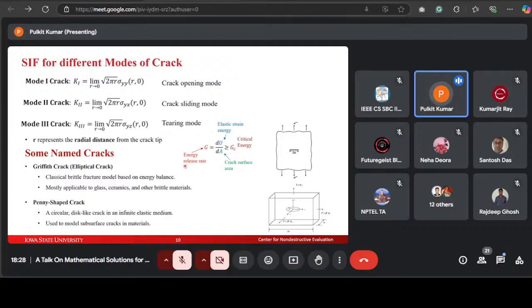Now for the Griffith crack, the total energy is equal to the strain energy and the surface energy. The crack propagates when the release of the elastic strain energy exceeds the energy required to form new crack surfaces. So mathematically, Griffith's energy balance is given by G equals dU over dA, which should be greater than or equal to the critical energy.